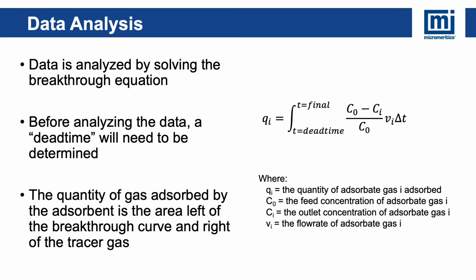So how do we actually analyze our data? We do that by solving the breakthrough equation shown on the right. The breakthrough equation is an integral from the T dead time, which we'll talk about on the next slide, to the T final, which is when we reach saturation. We then multiply by a normalized concentration, multiply again by a molar flow rate, and then integrate over the time. Before analyzing the data, a dead time will need to be determined. All in all, as we saw before on a breakthrough curve, put simply, the quantity of gas adsorbed by the adsorbent is the area to the left of the breakthrough curve, and if you're using a tracer gas, it would be the right of the tracer gas.